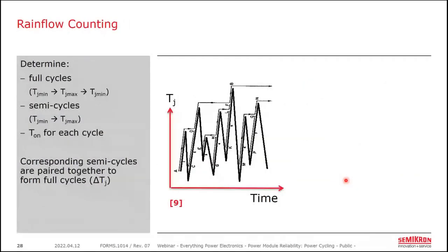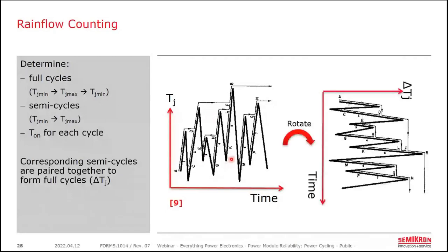Now, rainflow counting is pretty complicated and deserves an entire lesson unto itself, but I'm going to try and summarize it for you here. This method was developed back in the 1960s and into the 70s by a Mr. Endo and a Mr. Matsuishi in Japan as a method of analyzing mechanical fatigue data. And when we apply that to our temperature data, the basic idea is that you plot the junction temperature versus time, and we can rotate this 90 degrees, and you get this shape here that looks a lot like the roof of a pagoda, which is a building design in Asia.